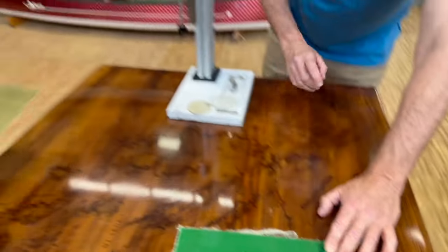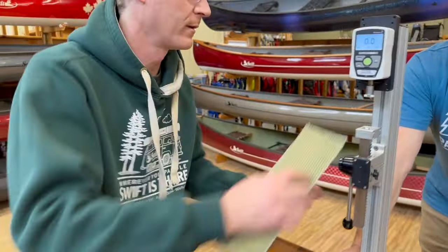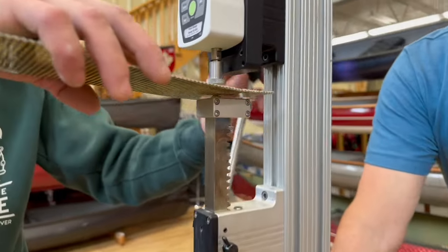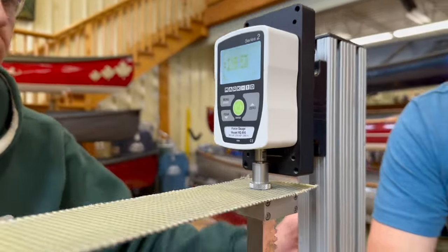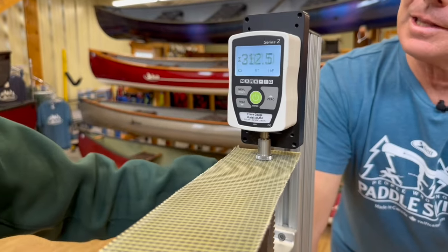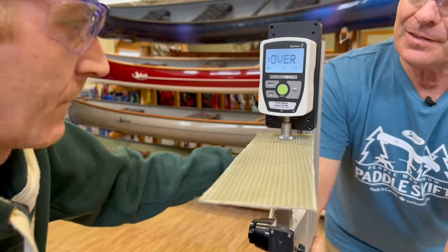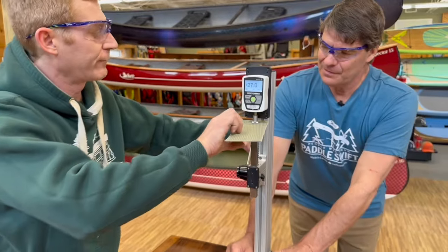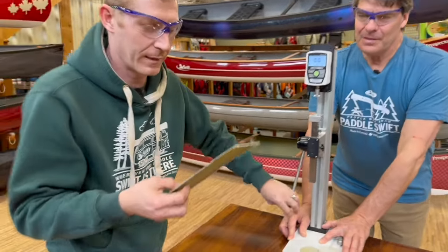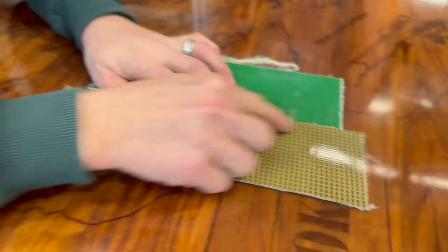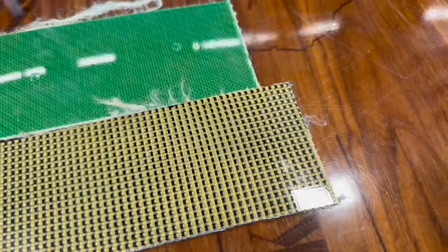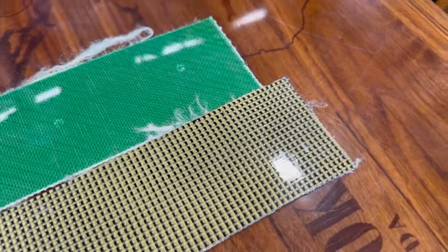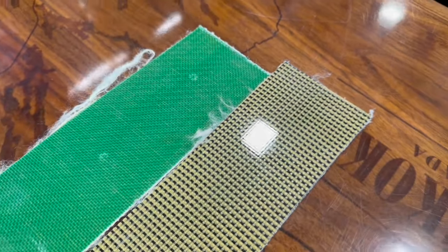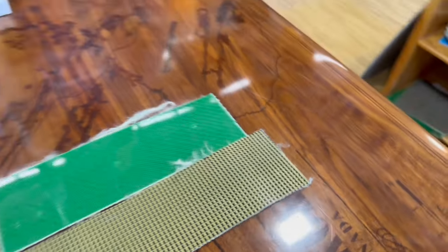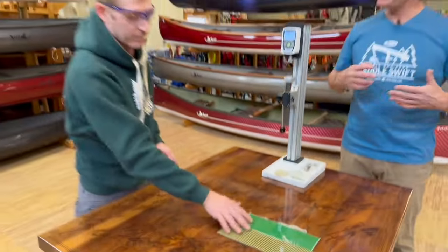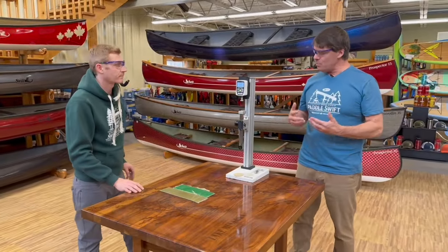So now we're going to do the same test on our epoxy. So guys, 500 pounds on a little small object like that is a huge impact. That is gigantic. So there we go. We've got another 550 pounds now on our epoxy laminate. And we can see that we have barely even left a mark of the screw on top of there. So we're seeing some significant impact resistance, and with the epoxy, it's quite incredible. So the epoxy can take way, way more of a beating.